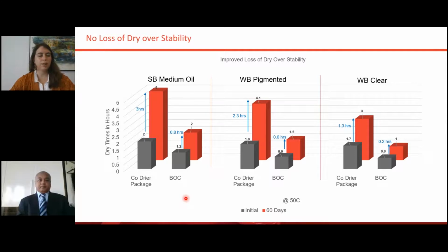Another point I talked on is no loss of dry over stability. So what we do, the gray is the initial dry time. We took the paint, threw it down, and recorded the dry time. The red is after 60 days of stability at 50 degrees Celsius, so the wet paint was in an oven for 60 days. We reapplied it and measured the cure time. This really correlates to a few years of this paint being on the shelf.